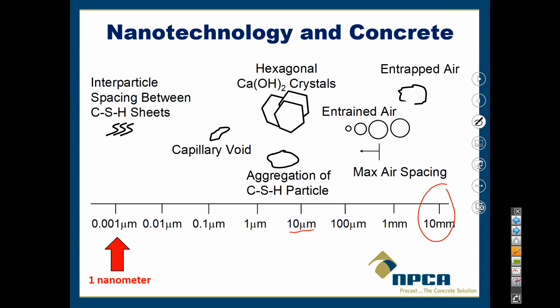And when we get to pores that are that size, they exist in concrete and typically encapsulate water. So some of the water you'll use today in your concrete is going to get trapped in these very, very small nanometer scale pores, and they'll get trapped there forever. They're not going to be available to use for hydration. And this creates these gel pores, these very small pores, that does affect, to a certain point, the durability and strength of the concrete.